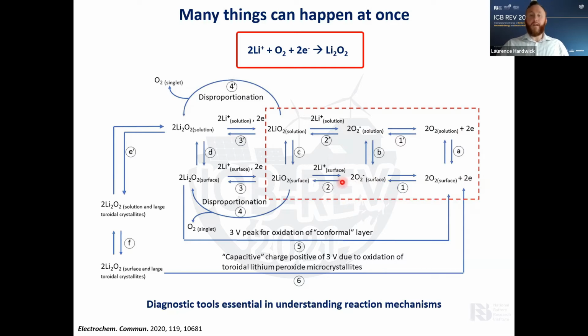And so once on the surface, it can react with lithium and form lithium superoxide. And again, it can then disproportionate, and you can form singlet oxygen, and you can then form these various forms of molecular peroxide, a very thin layer of peroxide on the surface, or if it's in solution, it can precipitate out and form very large crystallites of the peroxide. So this just highlights why we need these diagnostic tools in pinning down and understanding these reaction mechanisms, and understanding, if we do vary certain parts of the solvent with its different donor or acceptor numbers, how that influences these reactions.